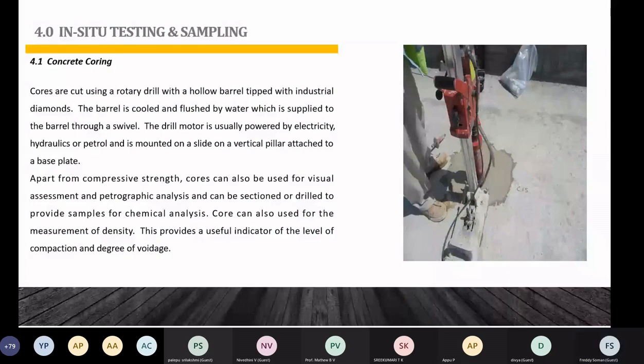That is why we normally go for special accreditation for concrete coring and core testing. Because if a lab is not properly doing the core test, it can give misleading values. Sometimes good concrete will give a bad result, a low strength value, because the core should be properly taken and properly prepared, particularly the ends properly cut, the flatness checked, and the perpendicularity of the core checked. It's a very important test. Apart from compressive strength, as I mentioned earlier, cores can also be used for visual assessment and petrographic analysis as well.